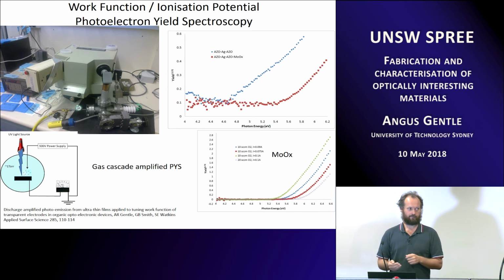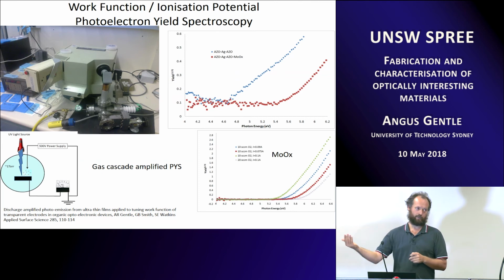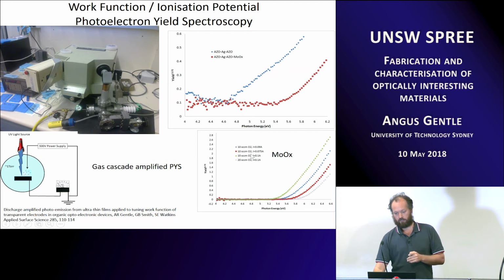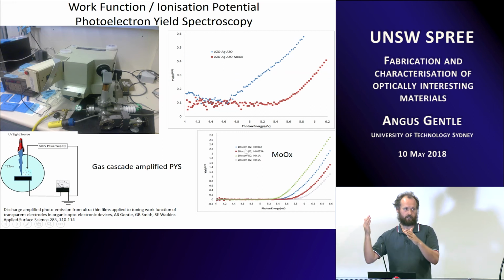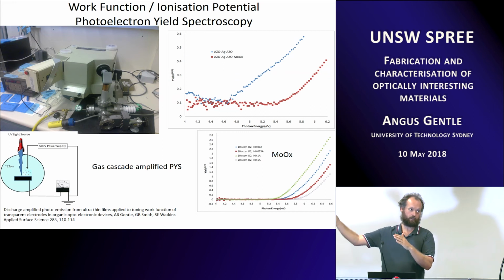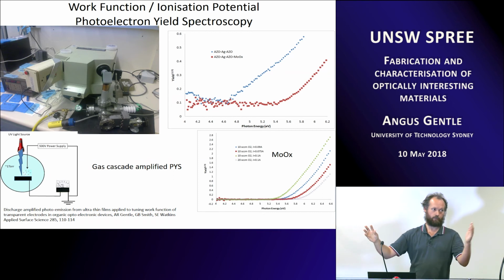If you sputter it, if you start with a metal target or an oxide target, you've got to either reduce or oxidize as you go. So this is some stuff we're looking at, starting with a metal target, changing the oxygen flow rate to get different from MoO3 down to where we need.